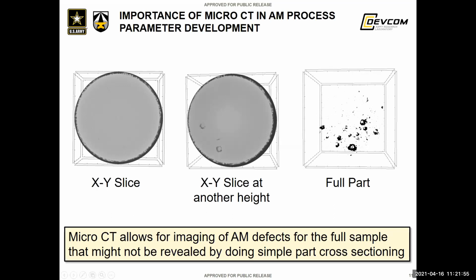Not to detract from doing optical characterization, because it's still beneficial, since with CT we are limited by the voxel size, which is usually limited by the size of the object itself, as well as the density of the object. For example, this high strength steel is at the very edge of what is usable density-wise in the machine, so I usually have to hit it with the full wattage, and it takes several seconds per image. Whereas if I did it on an aluminum part, I would be able to get results in a third of the time.